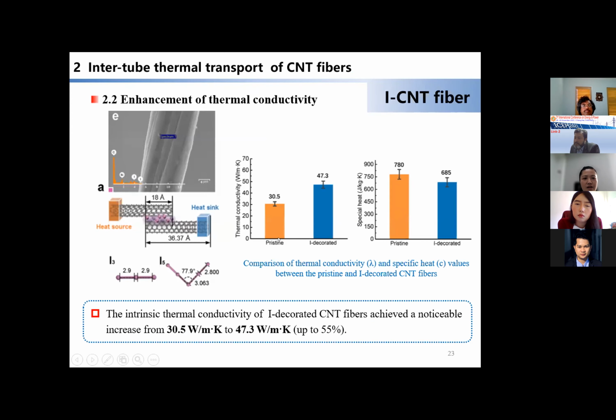Similarly, for iodine decorated fiber, this bar clearly shows that the intrinsic thermal conductivity of iodine decorated CNT fibers achieves a noticeable increase of up to 55%.